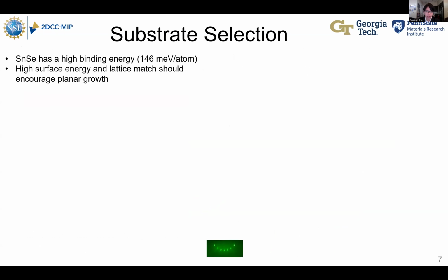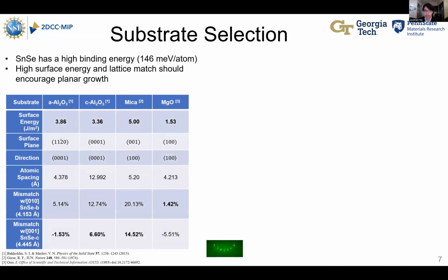One of the first steps to growing our film is to figure out what substrates we want to grow on. One of the challenges is that tin selenide has a very high binding energy. In comparison, MoS2 has a binding energy of 23. This has a binding energy of 146. So what this means is that a high surface energy and lattice match should encourage the planar growth of this material. So we looked at four different substrates that have close lattice matches and that have been used for thin film materials. These are A-plane sapphire, C-plane sapphire, mica, and magnesium oxide.